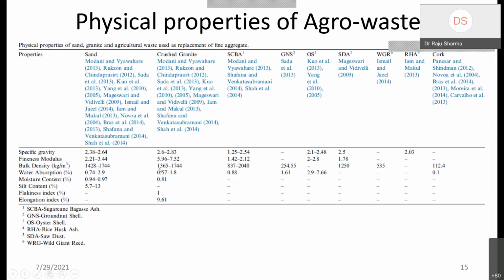So you can see that the fineness modulus of crushed granite acts like a coarse aggregate right here. So you can identify from here. But SCBA is a kind of sand, 1.42 to 2.12. Then OS is 2 to 2.8, and SDA is 1.7. So you can see here the oyster shell has a very similar property to the sand.